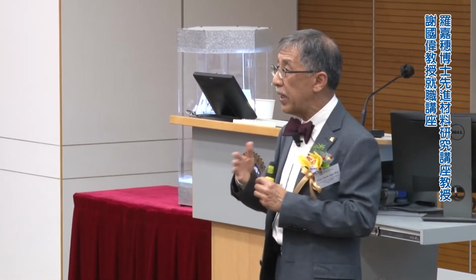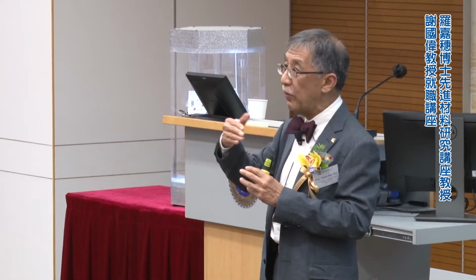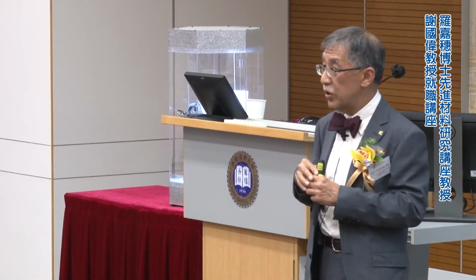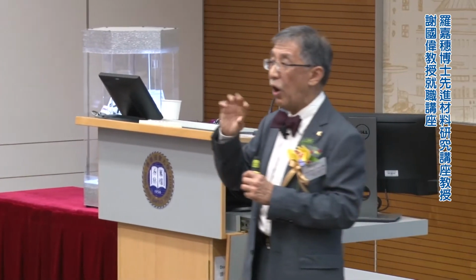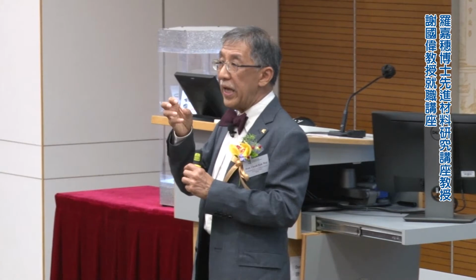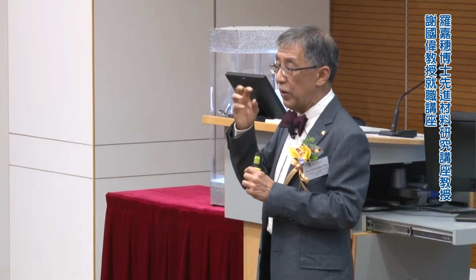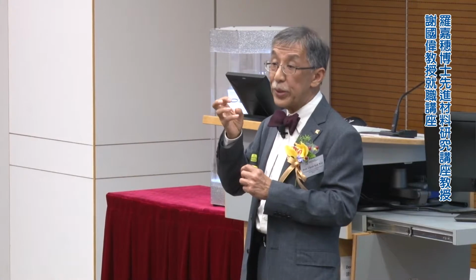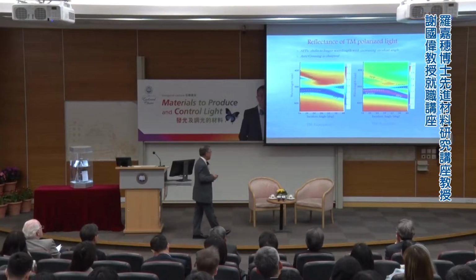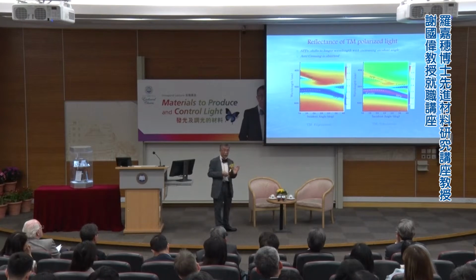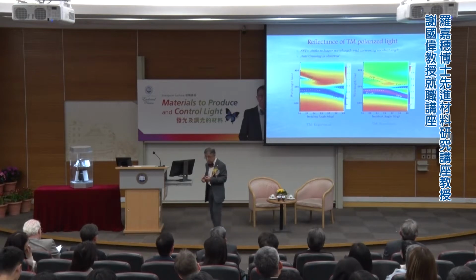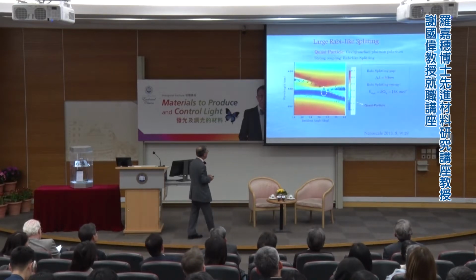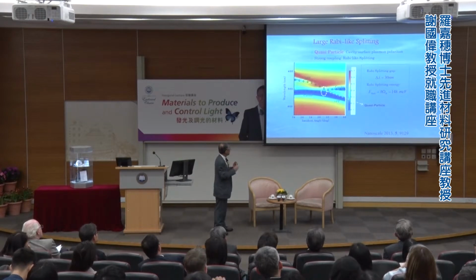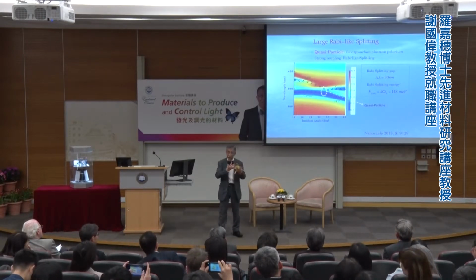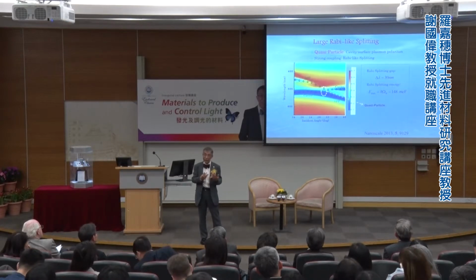That gap can allow light to transmit or reflect light, depending on how you look at it. So you can open up a gap very, very fast, in what we call femtoseconds. Very fast optical switching this way. And this way you can actually control where to do it, what wavelength, and how fast you can do it. So it's a kind of optical switching mode. And it's the first time it has been shown that you can do that using plasmonic or metamaterial.